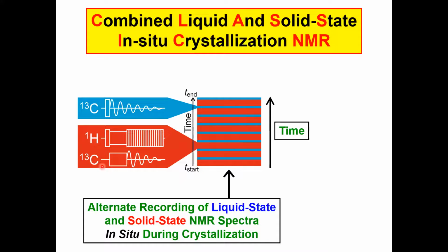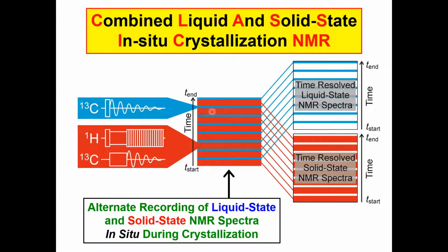So this is the strategy here. We have two different pulse sequences. One might be cross-polarization, as described before, to measure the solid state NMR spectrum. The other might be direct polarization with short recycle delay, or maybe without proton decoupling, to measure the liquid state NMR spectrum selectively. So we alternate between two different pulse sequences during the crystallization experiment, and then at the end of the experiment, we separate these into two sets of time-resolved spectra, one set of time-resolved solid state NMR spectra, and one set of time-resolved liquid state NMR spectra.